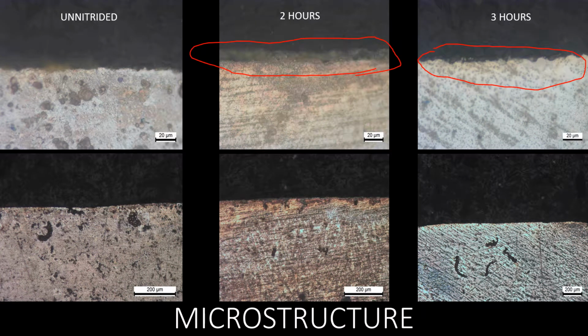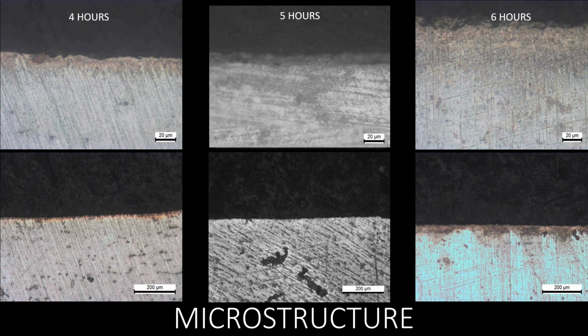It also shows the same case for the 4 hours, 5 hours, and 6 hours of nitriding time, where we can see a boundary, a layer between the phenolic powder and the material itself. So in the 4 hours, we can see around here, 5 hours is around here, and 6 hours is around here. However, it's worth noting that the layers are shown clearer in the SEM imaging process.